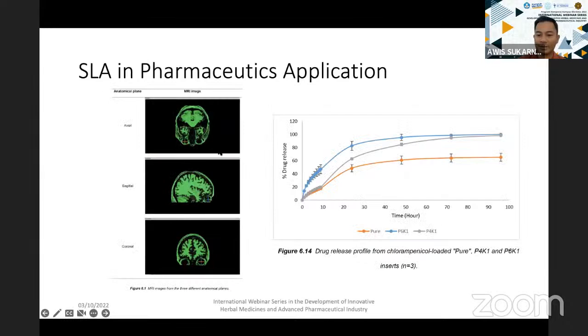After that, I created this insert based on the MRI, and then I tested the drug release. As you can see here, for the first formulation using polyethylene glycol 6000, PEG 6000, the release profile is quite a bit faster compared to the others. This one is PEG 4000, and this one is without the PEG. With the addition of PEG 6000, it shows a faster release profile, and then it starts to plateau.